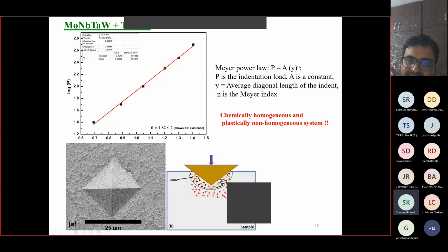This is a schematic of what exactly happens in different phases with respect to dislocation interaction between the tip and the material. And this is a chemically homogeneous material because all the phases have all the elements, but plastically non-homogeneous in the sense that you have one BCC phase and two FCC phases. The plastic deformation in the FCC phase is really good, but the BCC phase is not that easily deformable. Plus, it also exerts back stress on the FCC phases. So that brings the overall plastic non-homogeneity in the system.